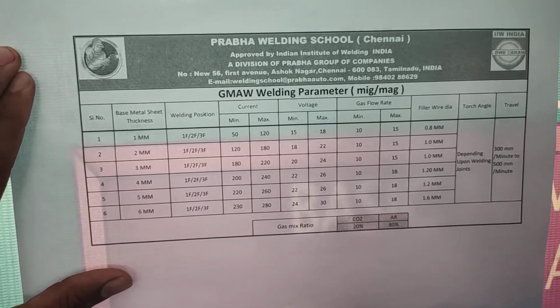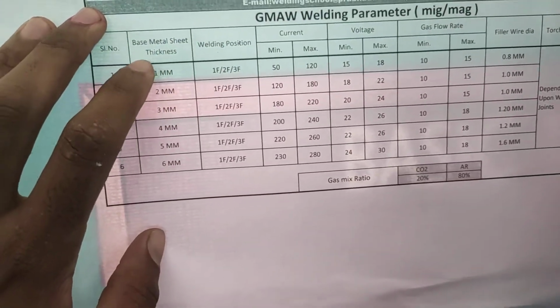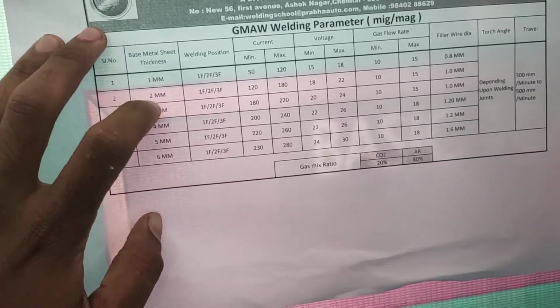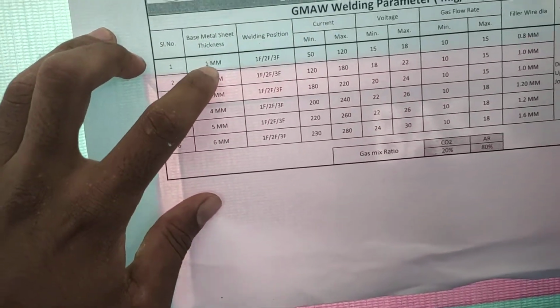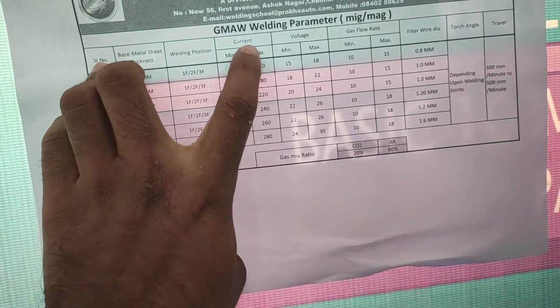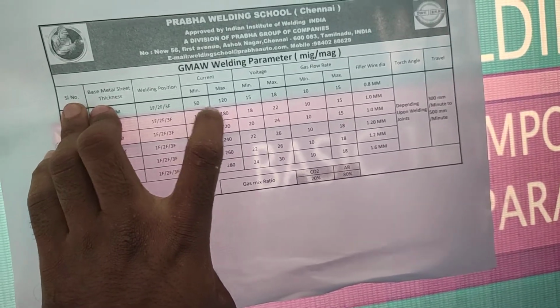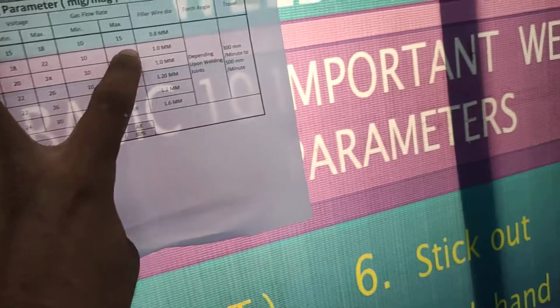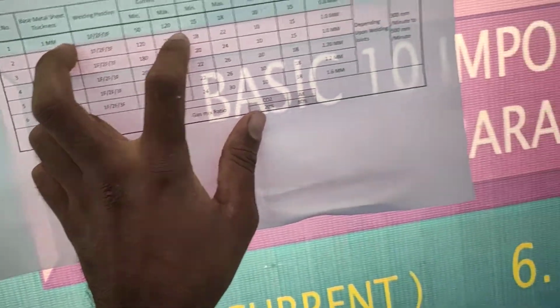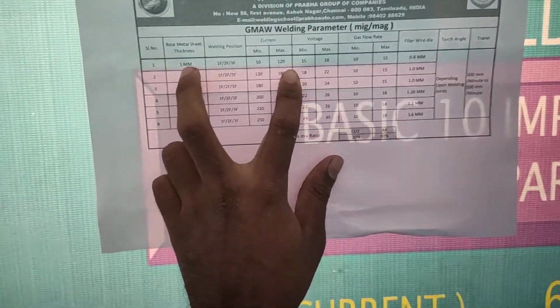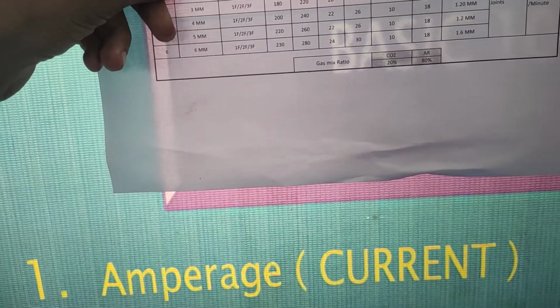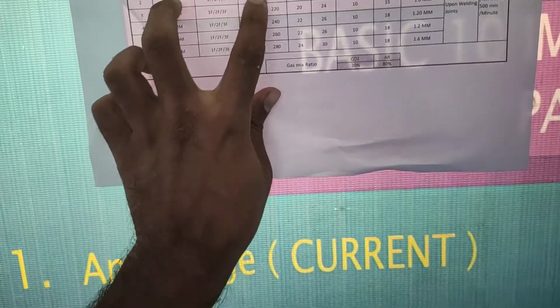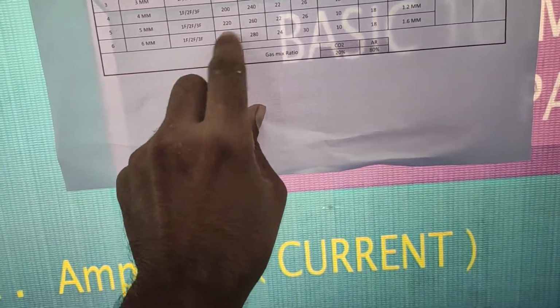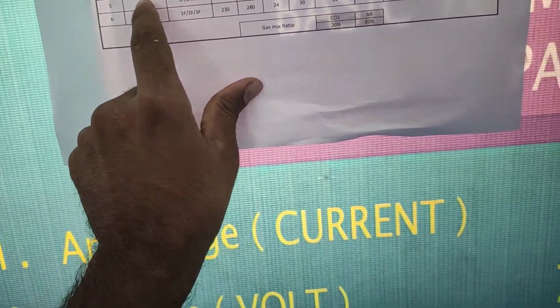Now you see this. This is the base material, thick carbon steel. This is a carbon steel table. If we use 1 mm plate, the current, that means amps, is 50 to 120, voltage 15 to 18, gas flow rate 10 to 15, filler wire diameter 0.8 mm. For 2 mm, 3 mm, 4 mm plate, the current, voltage and gas flow rate increase depending upon the material thickness.